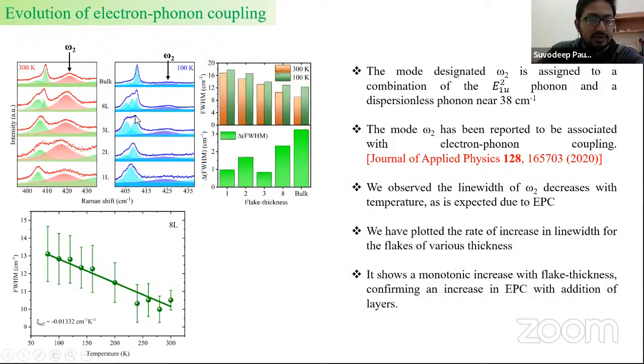What is also interesting is that this anomalous decrease in line width is seen for all the different thicknesses of MoS2 that we studied. And we also see that the anomaly increases as a function of thickness. So this again proves that with an increase in flake thickness, we get to see an increase in electron-phonon coupling, therefore confirming our previous assumption in the last slide. Further details of this work may be found in this paper.